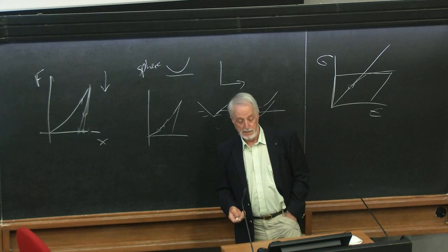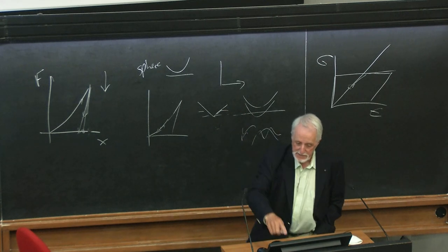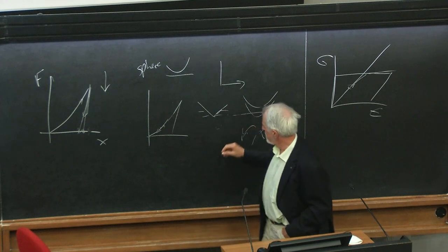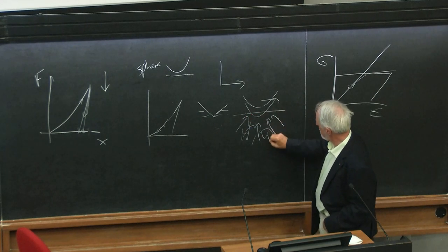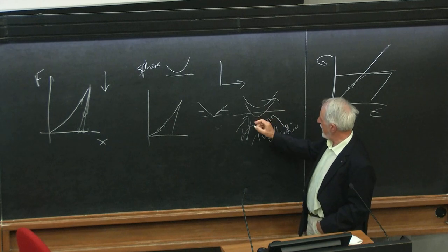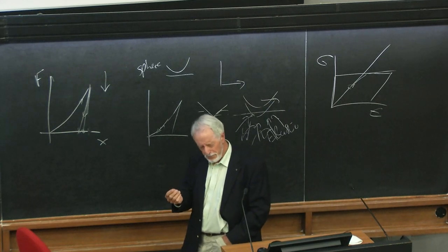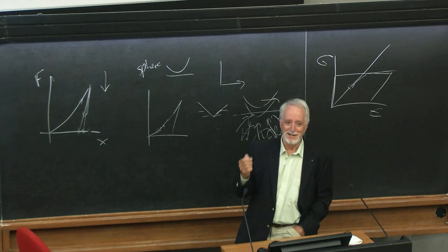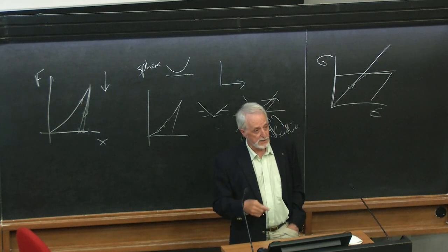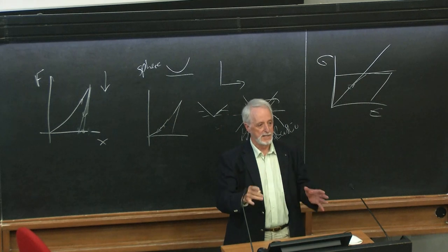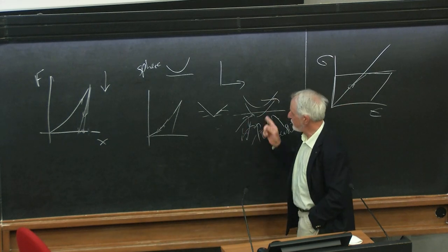What you find is that in fact, depending on the material here, and this is another story which I'm not going to be able to elaborate on, essentially what happens, I'll summarize this very briefly, it's easiest to see in these two sketches on the bottom right there. If you have a system which you've now pushed sideways, right, and it's got very significant elastic stresses pushing back, then what's going to happen is there's going to be some pushing that way, okay, which if it's a system which has a low value of the modulus over hardness, which is the same thing as essentially saying something which is highly elastic with not so much plastic energy put into it, when you deform it, a significant fraction is elastic, which is not true here, but is true here, right, depending on that slope, then you're going to get some process which pushes it back.